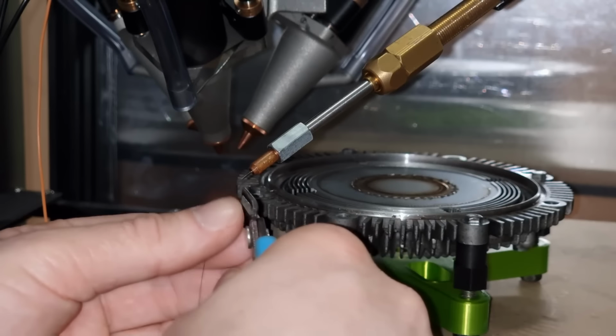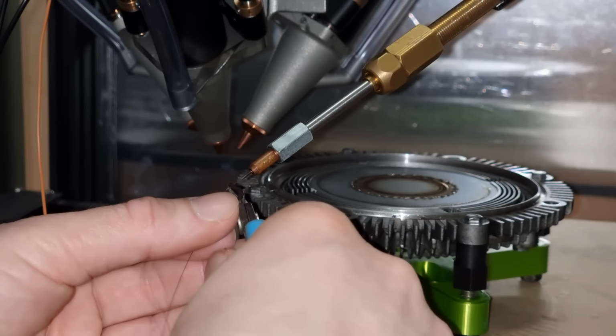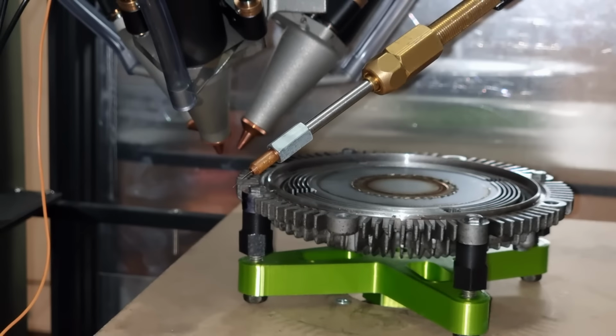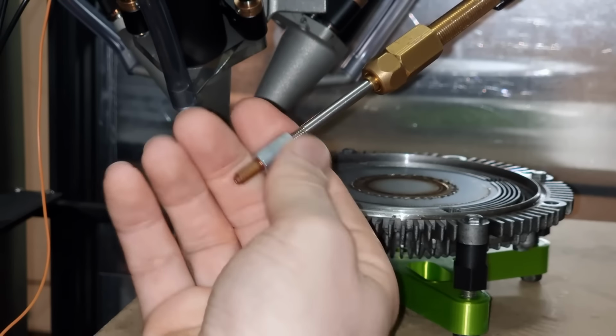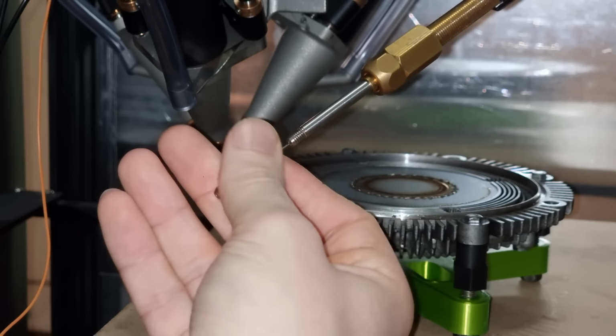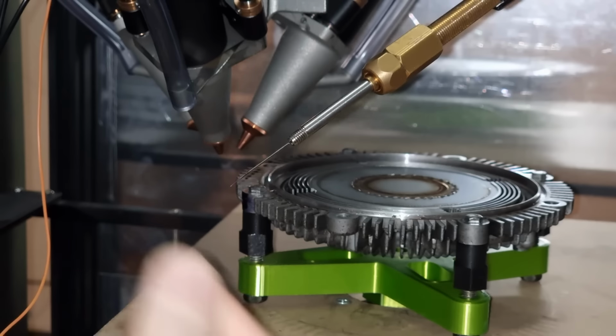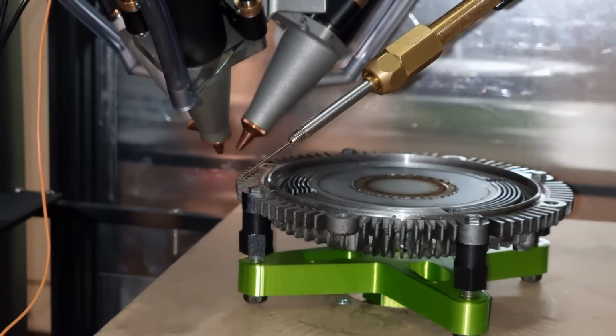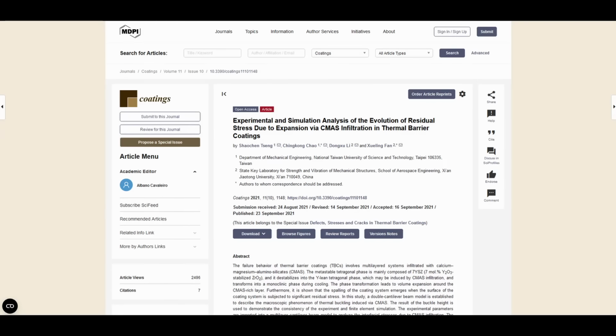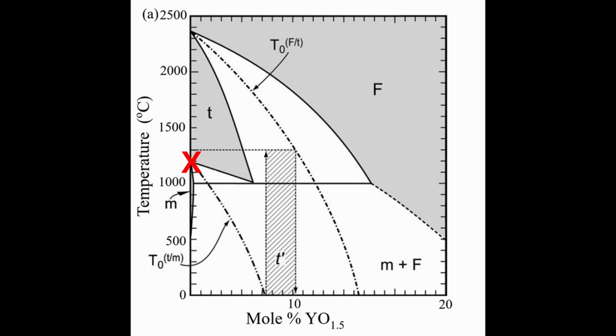I wanted to solve this by reducing the distance between the outlet of the nozzle and the substrate. Copper nozzles had worked okay so far as they reflect most light at 915 nanometers, but I couldn't find any with a fine enough bore and therefore would still have to sleeve them with syringes. Reflections would still see the feedstock bonding to the nozzle however, and to try and get around this I would use a fibre optic ferrule made from an inert material, in this case zirconia. Pure zirconia unfortunately undergoes a phase change at roughly 1200 degrees centigrade and is prone to cracking as a result.